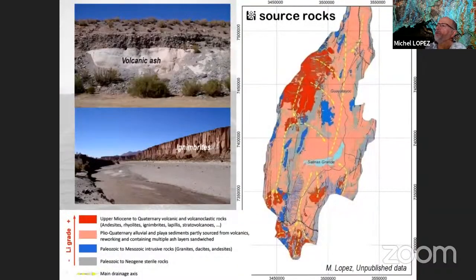So if we look at the source of the lithium, it is the same source as I proposed at the beginning. This is essentially, in the case of Salinas Grandes, volcanic ash and ignimbrites that were progressively leached, weathered, and released the lithium content. In particular, the volcanics are Miocene to Quaternary deposits. And here you can see the progressive convergence from the different parts of the basin leading to the input of this brine in the central part of the depositional system.